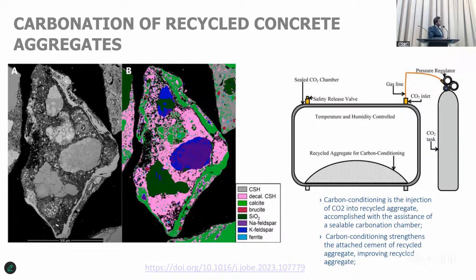So these are how we can get the recycled concrete aggregates. At the moment we can replace only about 30% of the coarse aggregates according to the specification. However, I'm leading a committee in our Australian standards subcommittee looking at a recycled concrete aggregates specification. By having carbonation like this, we can have an even higher percentage, maybe 50% of the coarse aggregates. We are running out of gravel, coarse and large aggregates, which can be replaced by this recycled concrete aggregate component.